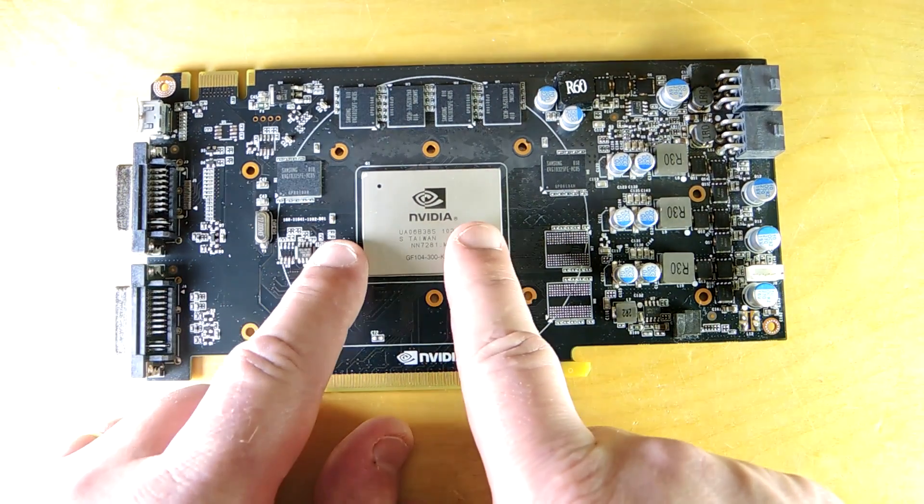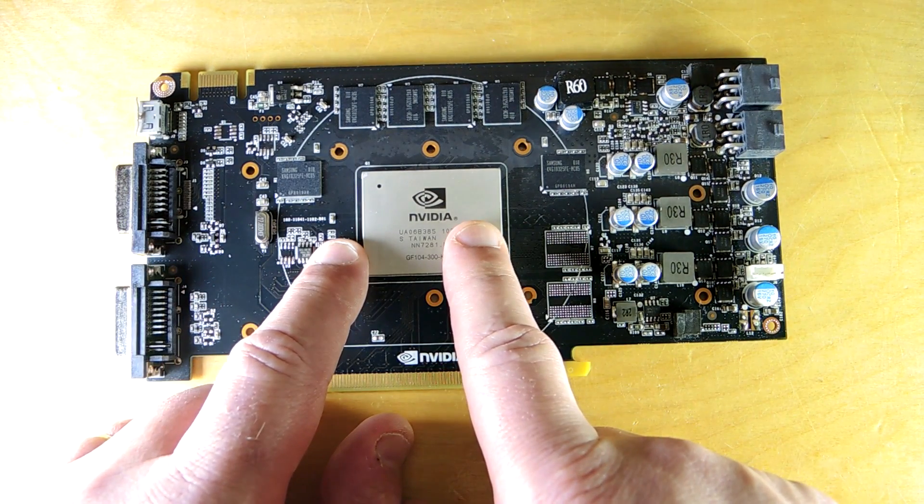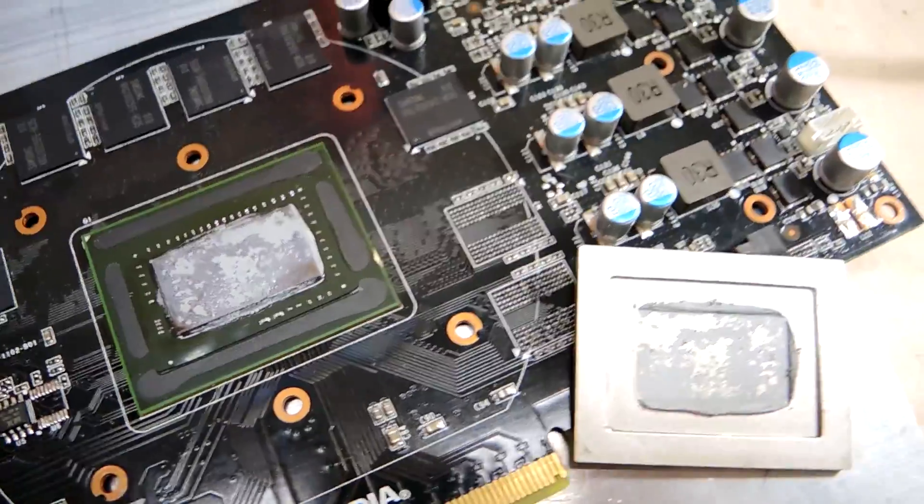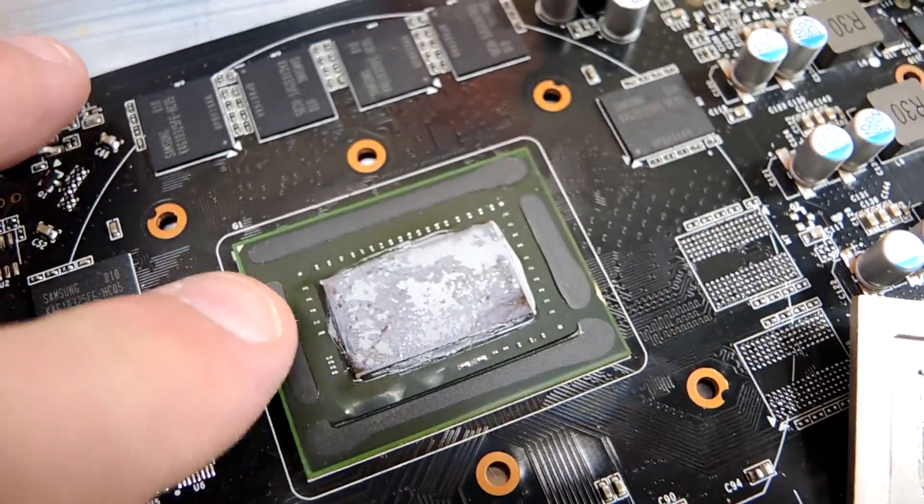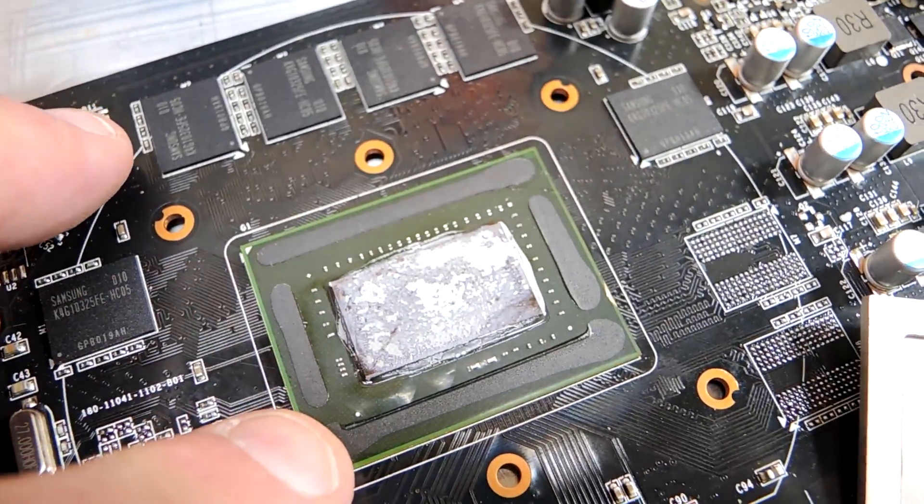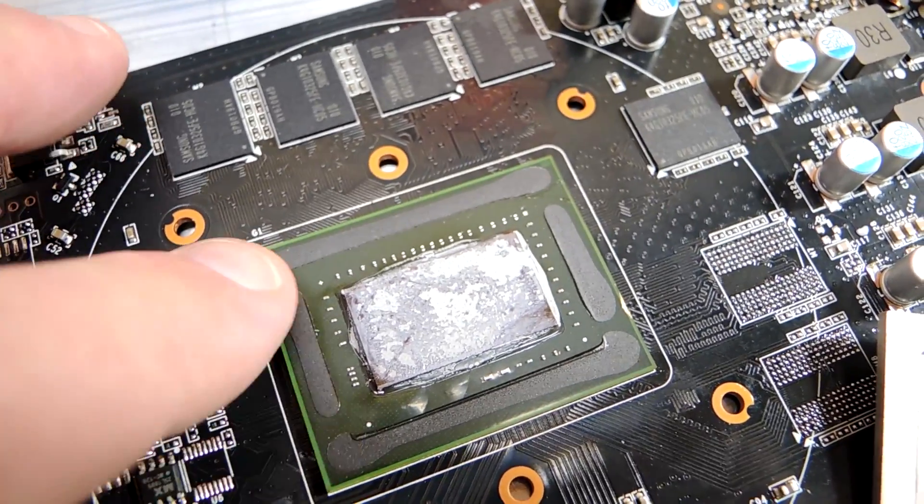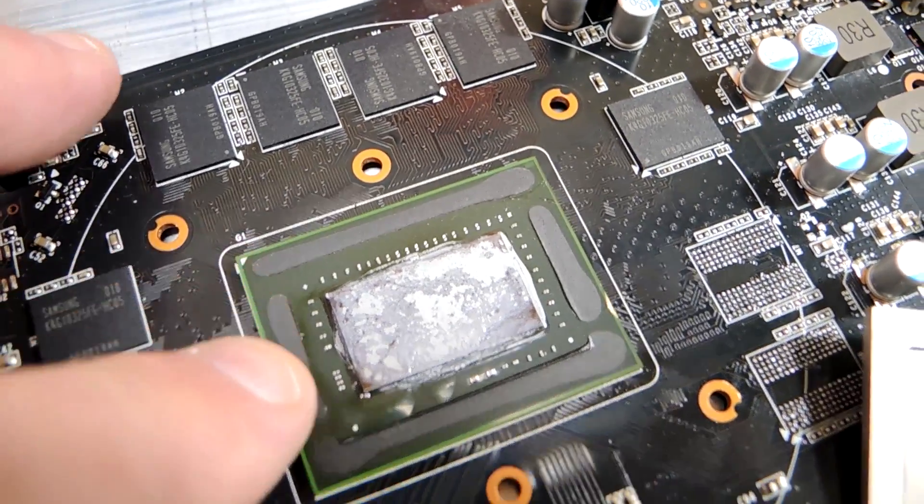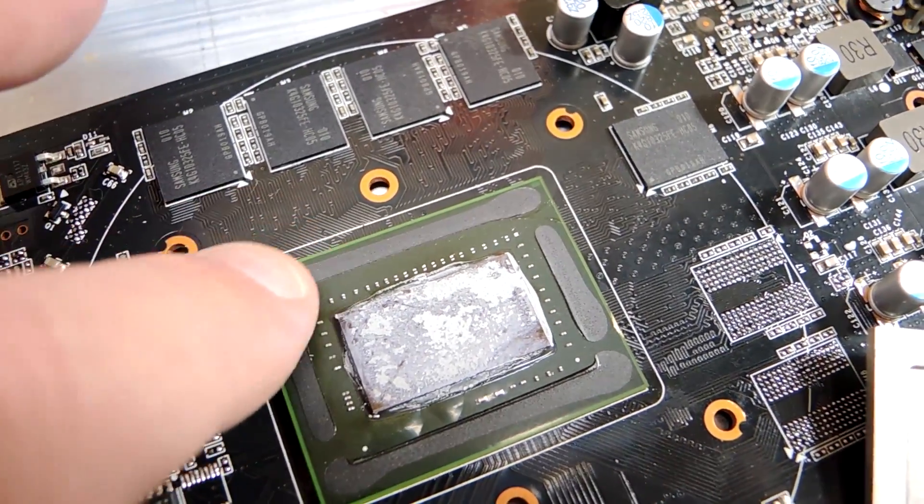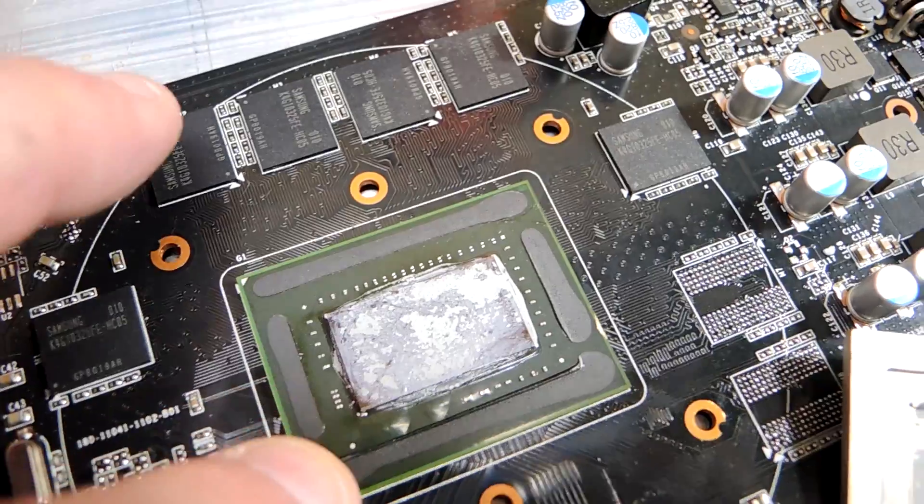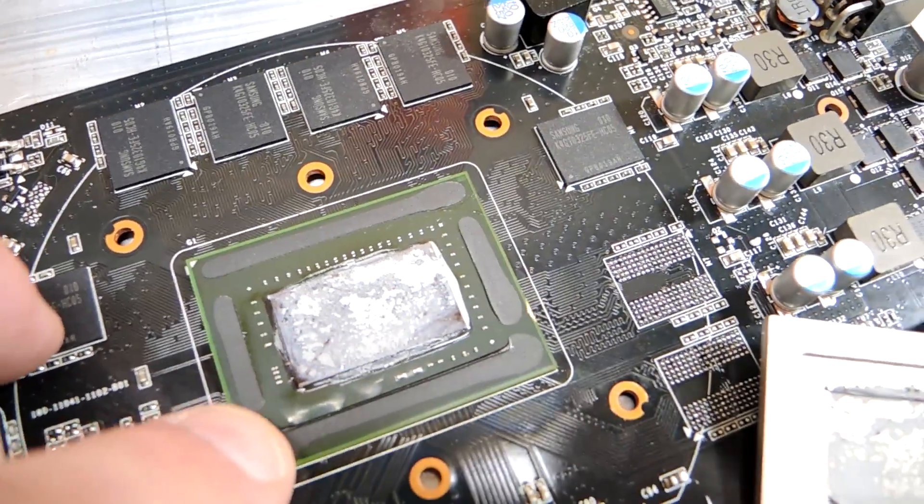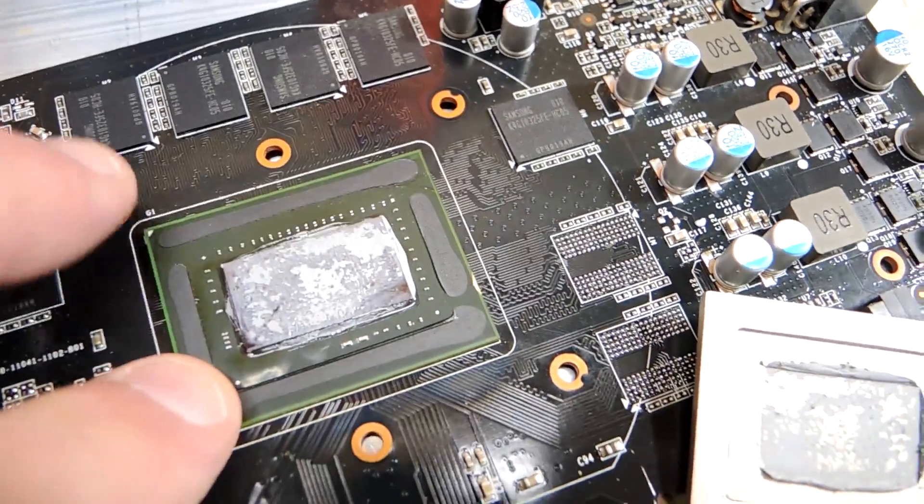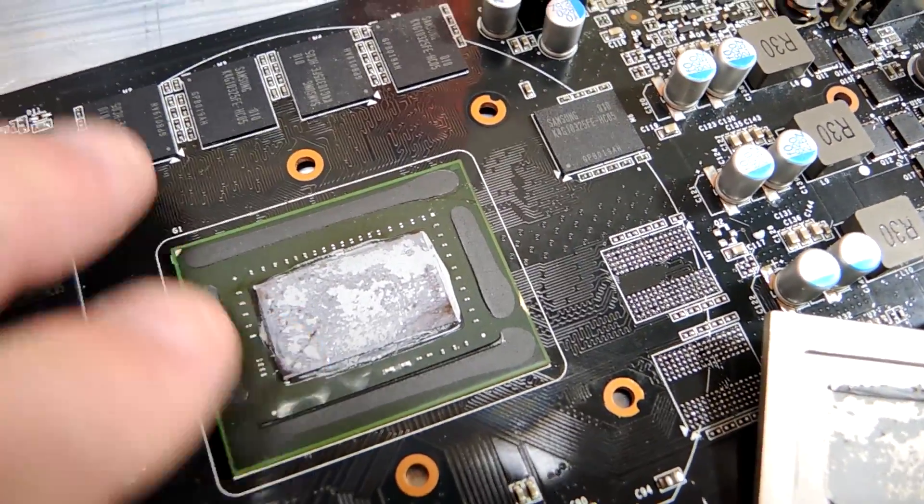Let's see if we can get the integrated circuit out here and see what it looks like. Okay, well, I got the lid removed. Basically, it's epoxy down to the substrate. The neat thing about epoxy is that they have something called the glass transition temperature. If you get them hot enough, the epoxy goes into a liquid-like state, and then you can pry things apart, usually without damage.